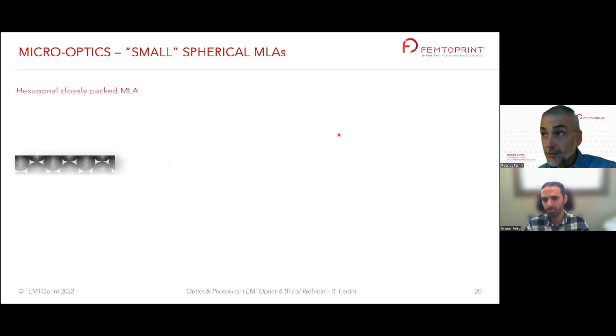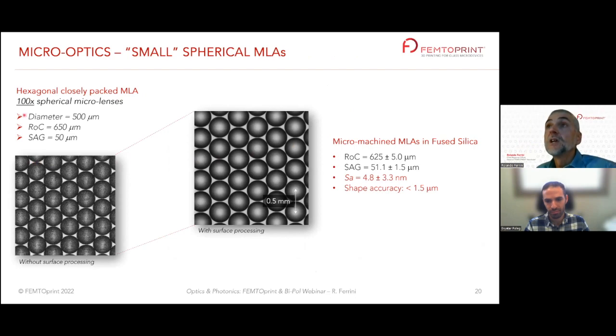So, concrete examples. This is what I call a small microlens array, so 100 lenslets, diameter 500 microns, sag 50 microns. You see here, after the first process it is super rough. Then we apply the post-process and we can get nicely the sag. We can get a very nice surface quality, average roughness, 5 nanometers. The price to pay is the shape accuracy.